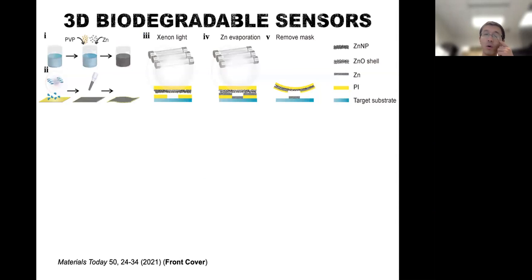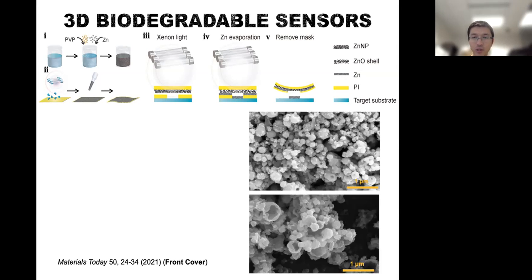So here, one interesting thing my student found out is when he used zinc nanoparticle and shone a xenon light, the material will be sintered in a very nice way and also get deposited onto the target geometry, whether flat or curvilinear in 3D geometry. And this is simply because only the zinc got transported onto the target geometry and the zinc oxide will be left behind. So it's probably easier to see from this SEM image with the zinc oxide on the outside surface